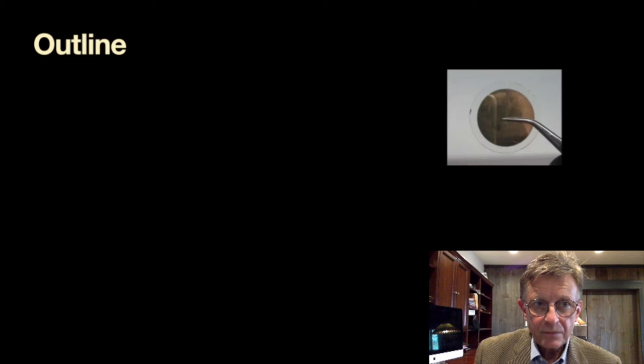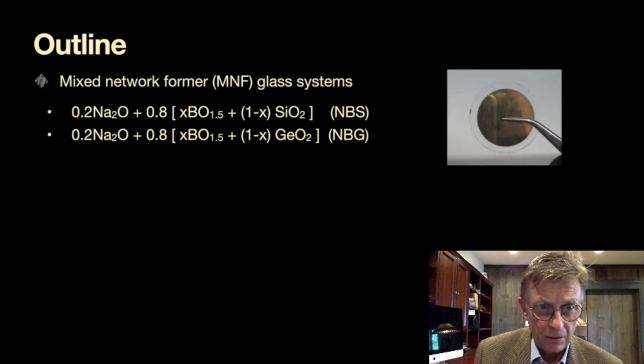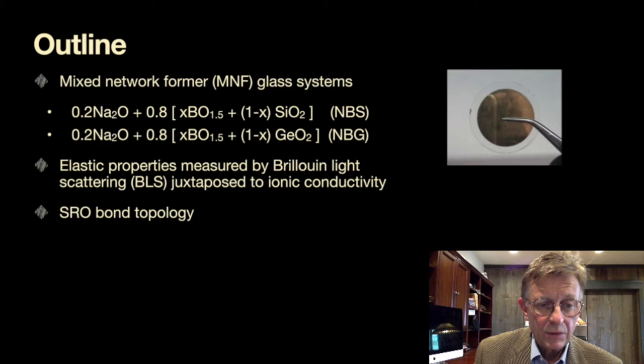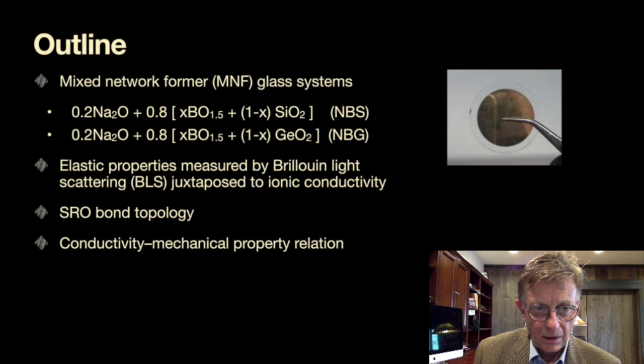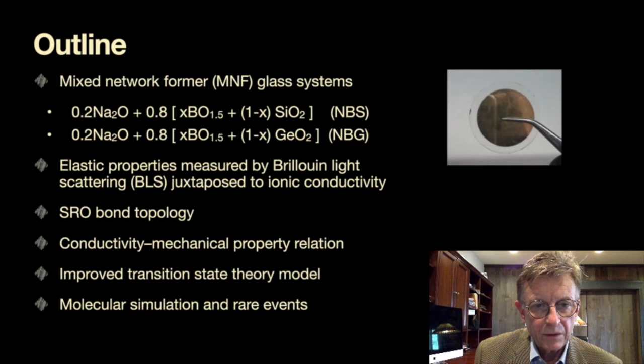The outline is that we'll talk about these mixed network former glasses. There are sodium borosilicates and borogermanates. Both series have 20% of sodium oxide and then there's an exchange between the two network former elements in each one of these groups. Important here is that we look at elastic properties juxtaposed to ion conductivity and that gives us information about the short-range order. It also shows that there's a strong correlation between conductivity and mechanical properties and this led to an improved transition state theory model and currently we are trying to improve that by doing molecular simulations on the same systems.